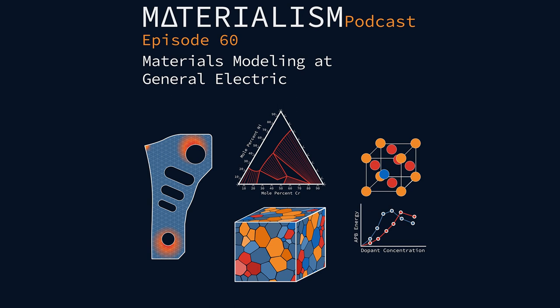And surprisingly, when they included this difference in the volumetric change, and therefore the strain that would accompany that, as a feature in their machine learning model, along with all the other traditional empirical models, they had a massive improvement. The model went from essentially being not useful, its R squared was something like 0.5, which was not powerful, and it jumped all the way up to 0.8, meaning that this was now a very actionable model. This was providing really actionable, great information.